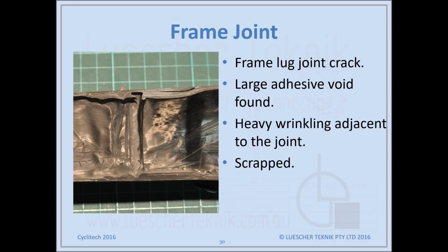Here we found a very large void in the adhesive joint through here. There's a very small bit of adhesive just at the edge, and that's what led to the crack indication, because there's no adhesive really backing it up. That adhesive void is quite large, so when the part was used, that area would flex.